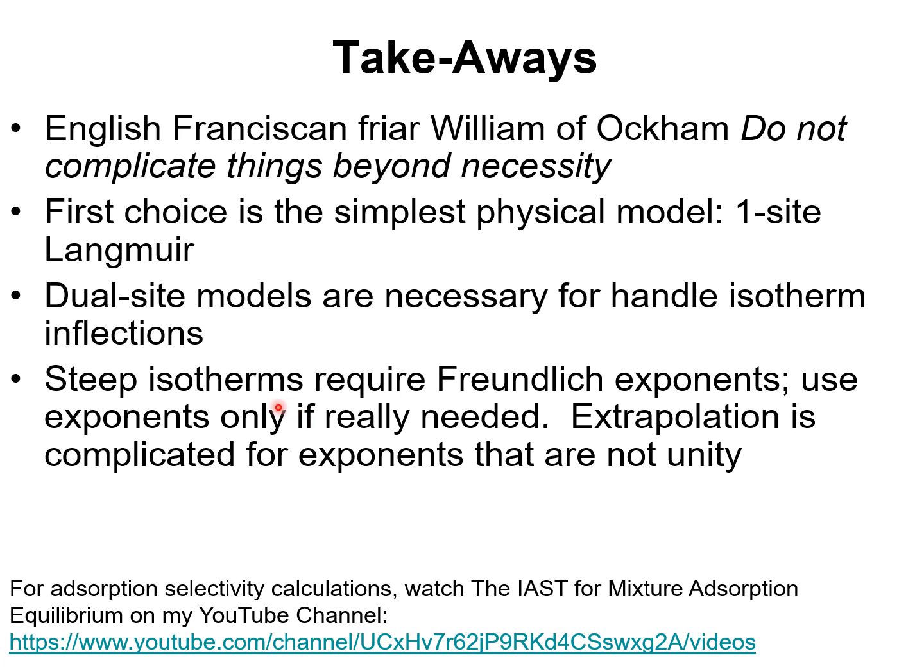If the isotherms show steepness, such steep isotherm behavior requires the Freundlich exponent to properly capture them. Such is the case with flexible MOFs or with guest molecules that undergo molecular clustering.